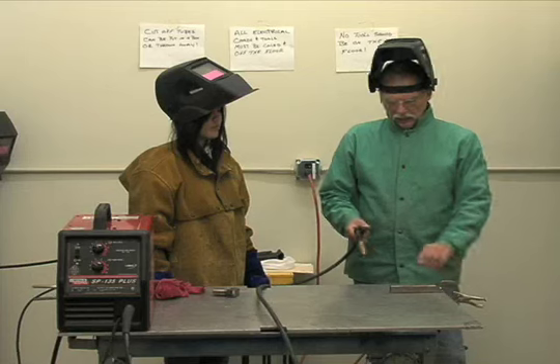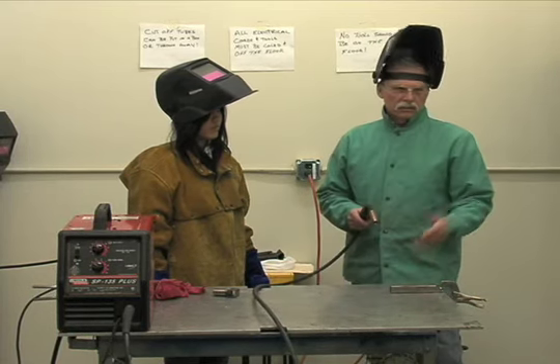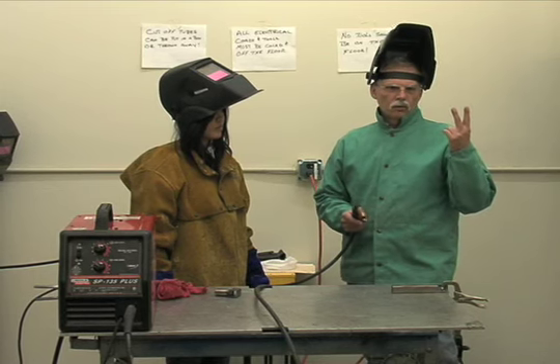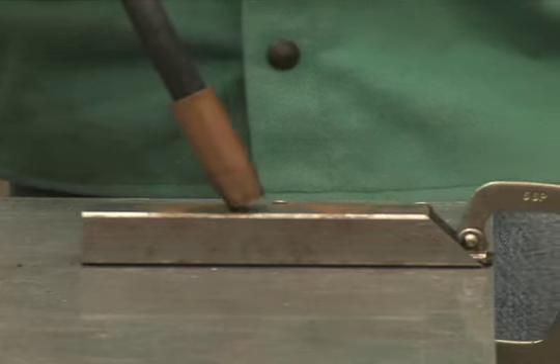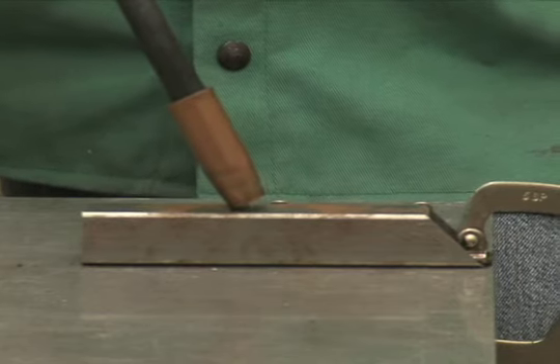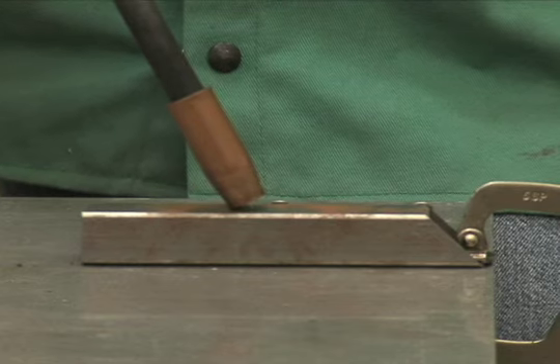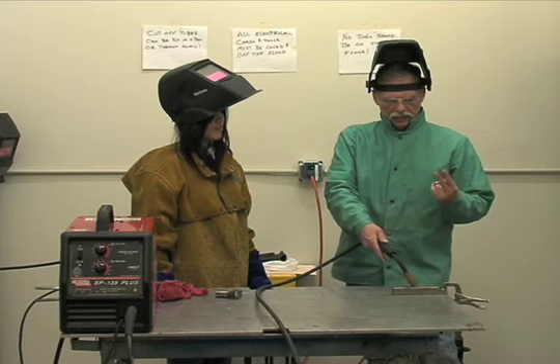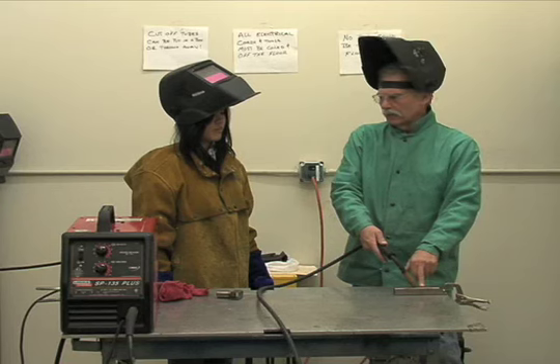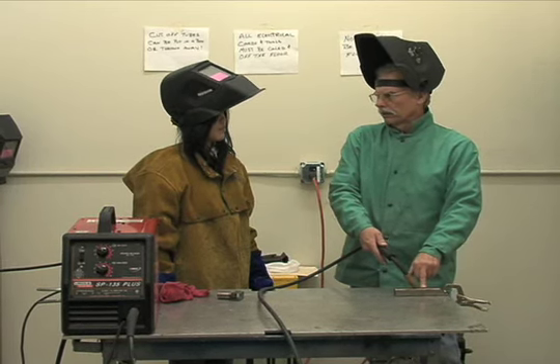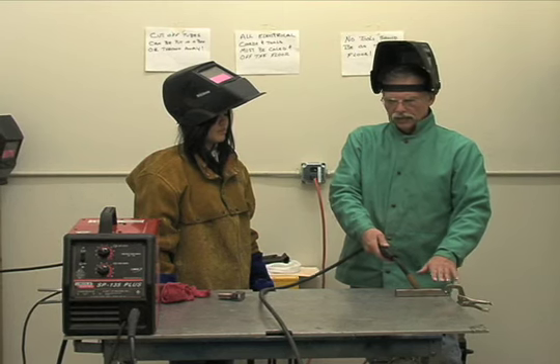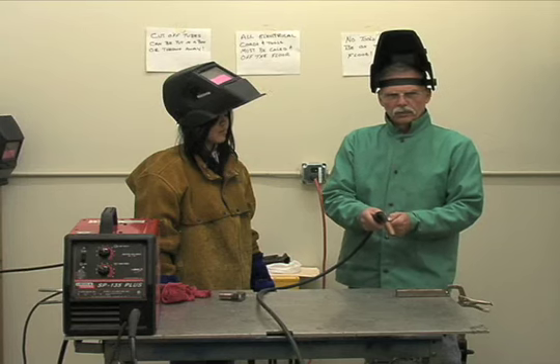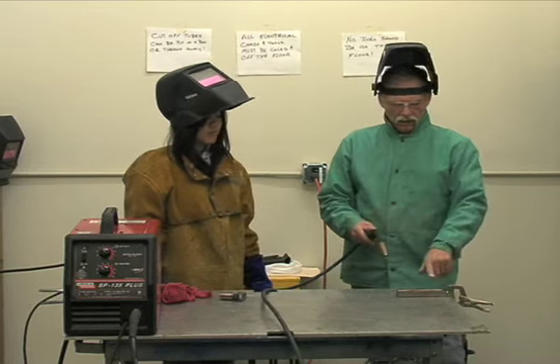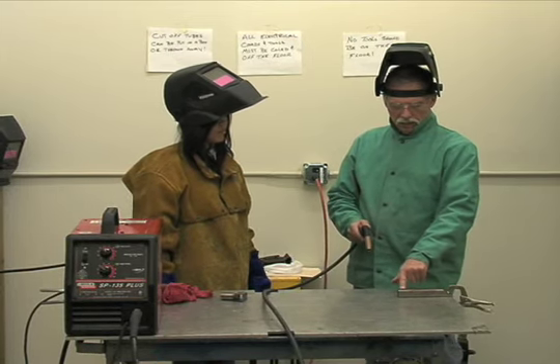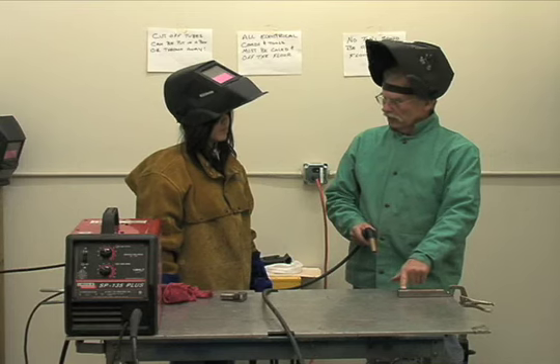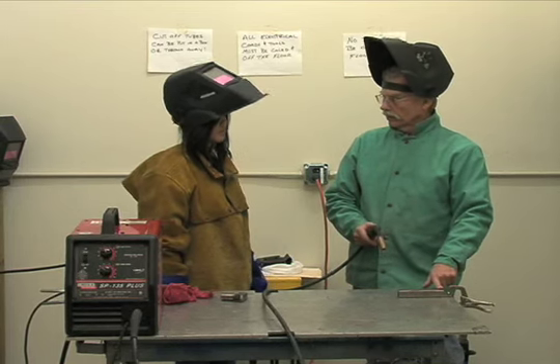The magic number for this material, which is 1.5 millimeters thick, is about 2 full seconds. We want to put it there and we want to pull the trigger 1 Mississippi, 2 Mississippi, release. That 2 full seconds will allow enough electrical energy to heat the metal up and create a spot weld that's proper. Any shorter than that, you'll have a cold spot weld with very, very poor adhesion, almost no penetration. Now, we'll do some, and I'll show you what a short one looks like, and what a medium one looks like, and what one that's long looks like.